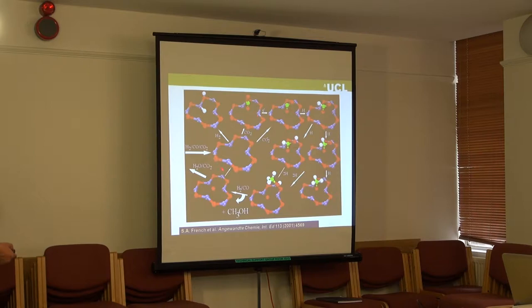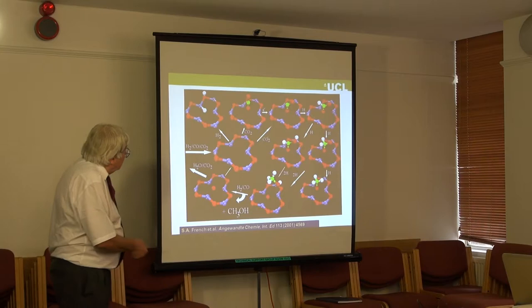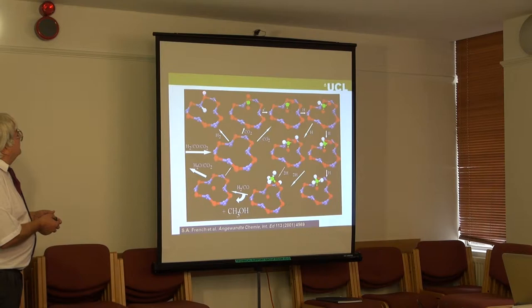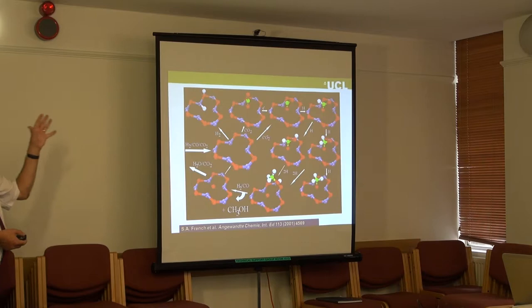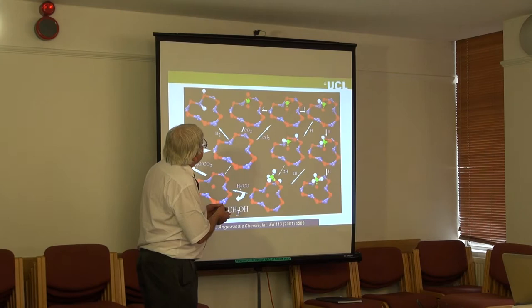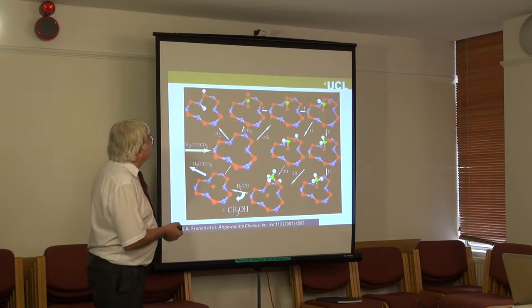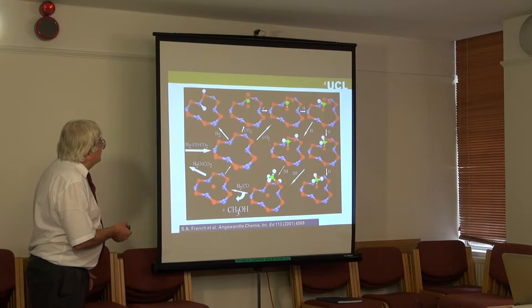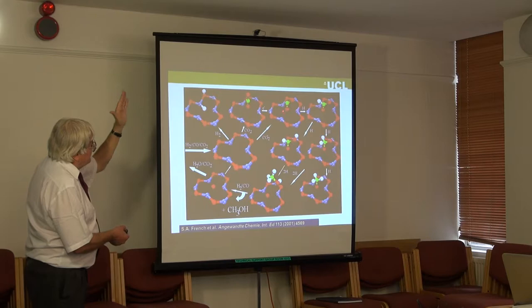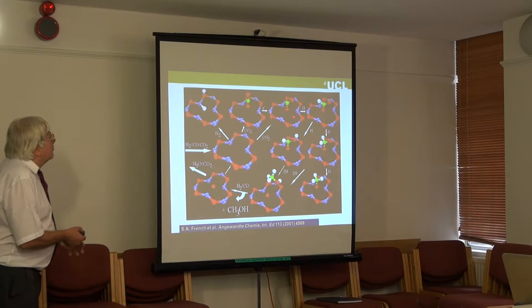Over ten years ago, Sam French, Alexei Sokol, and others pieced together a catalytic cycle. First we dissociate hydrogen; then we adsorb CO2 at this electron-trapping site, which is an absolutely crucial part of the catalysis. The electron is captured by the CO2 molecule and activates it. CO2 is a very inert linear molecule, but if you transfer this electron to CO2, you make CO2 minus — it bends and becomes activated. That defect — the electron trapped at the surface — is absolutely crucial because it activates the CO2.